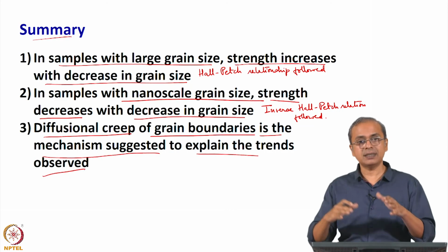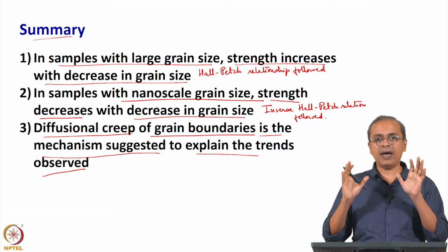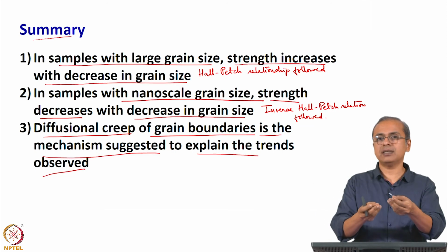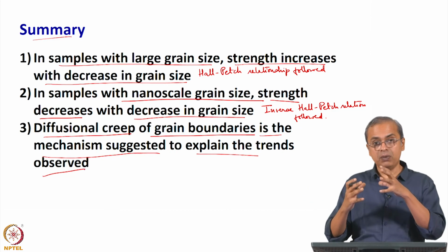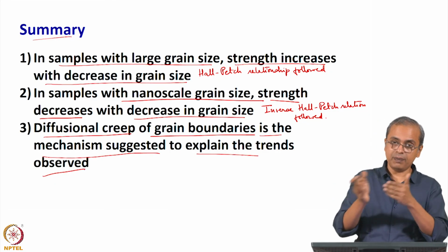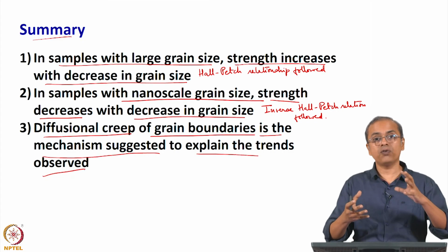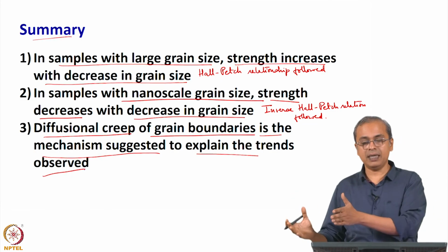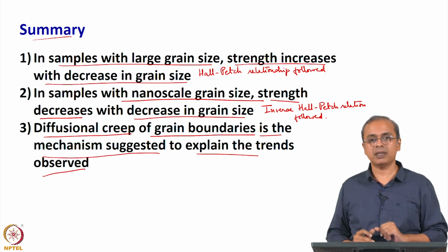However, in typical materials the amount of grain boundary that is available is less. Therefore, if you total up the number of atoms that are diffusing through the system, the fraction that diffuses through the grain boundary is less than the fraction that diffuses through the grain, and that is how you see the overall diffusion coefficient of that material. But when you have more and more grain boundaries, the fraction that is diffusing through the grain boundary keeps increasing, at some point equals or supersedes the amount that is going through the grains, and therefore you see the creep associated with the grain boundary, and if a phenomenon is being impacted by it, in this case the strength, the strength gets impacted by this diffusional creep.